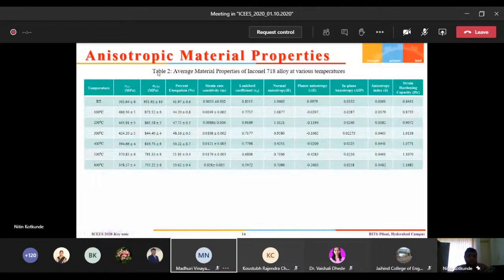Then we have characterized this. These are the average material properties. We have tested three times and taken the average with the percentage variation, and the important material properties which are usually required for further analysis, we have calculated, like yield strength, ultimate strength, percentage elongation, and strain rate sensitivity. If you see, strain rate sensitivity is very negligible in the case of Inconel alloys.